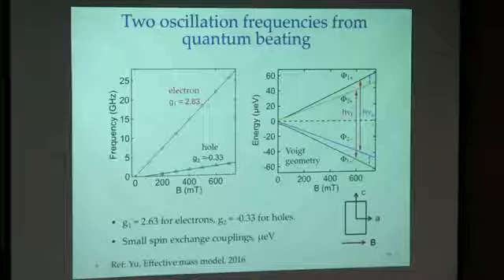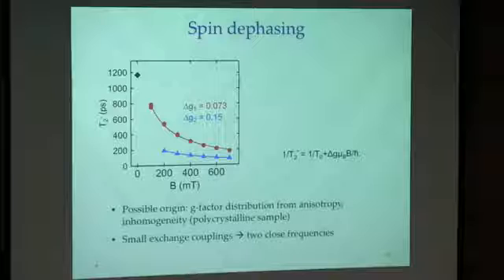What this means is that even with this complex description of the exciton states, the 2 frequencies now come down to those for electrons and holes independently. So approximately, the picture is that electrons and holes precess independently in the exciton. We like that picture as experimentalists. Further, I would like to show you more of the phenomena we observe in the polycrystalline samples.